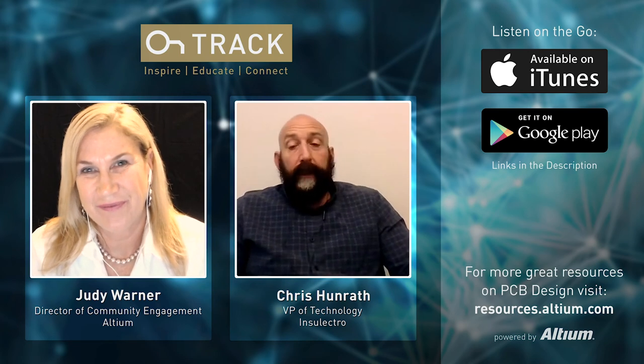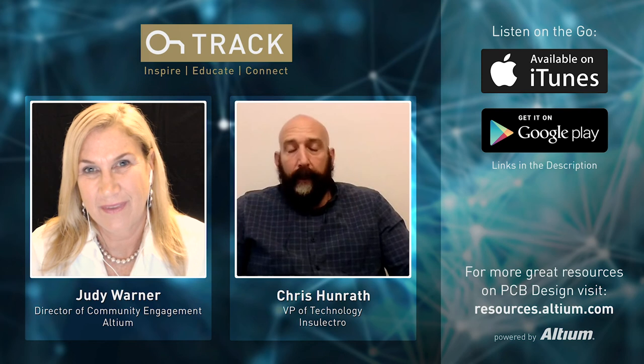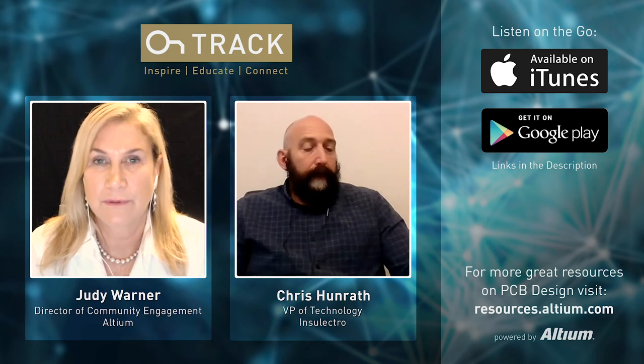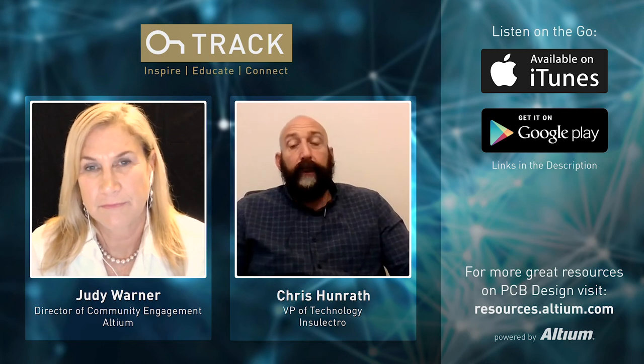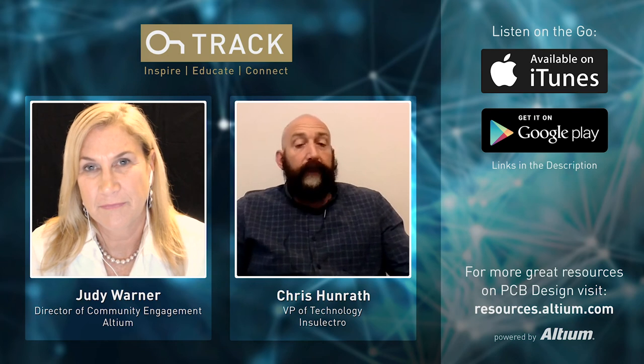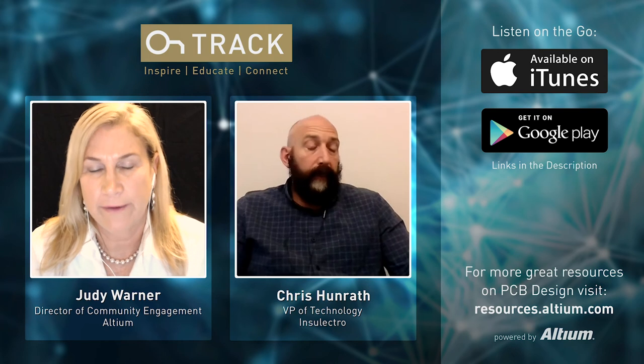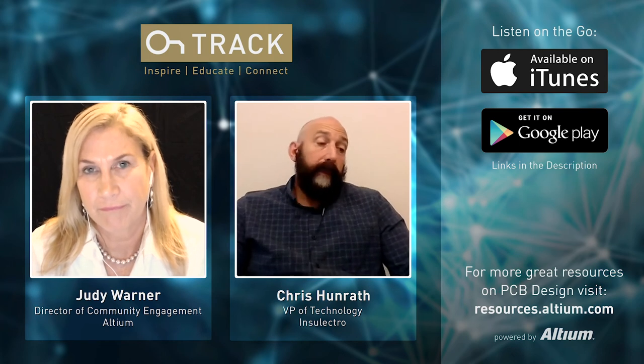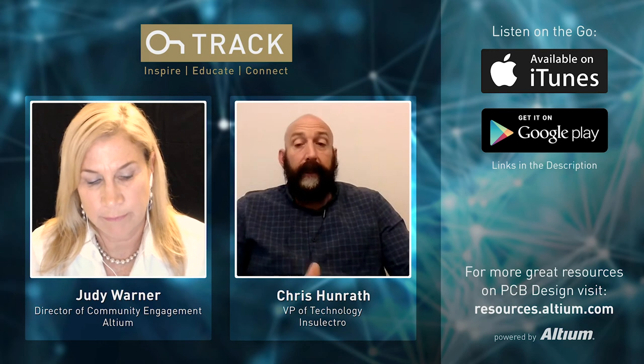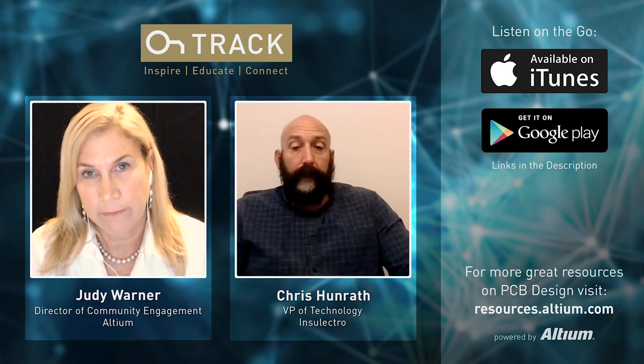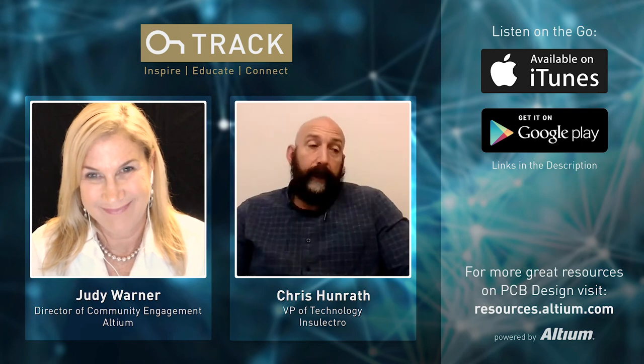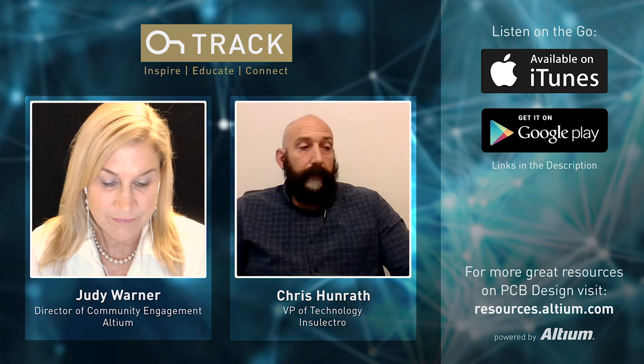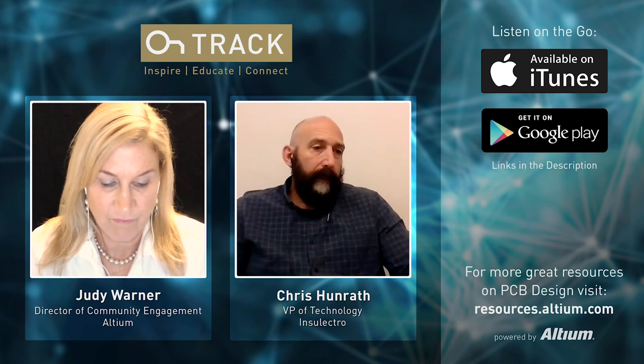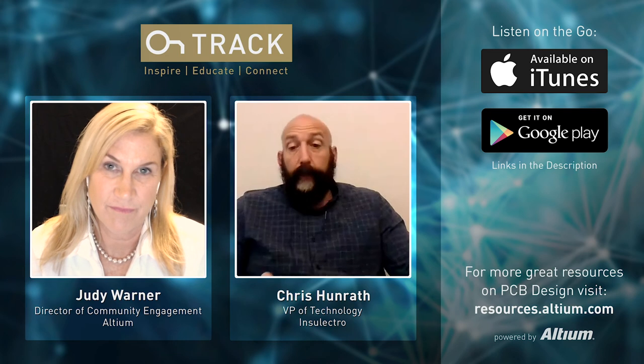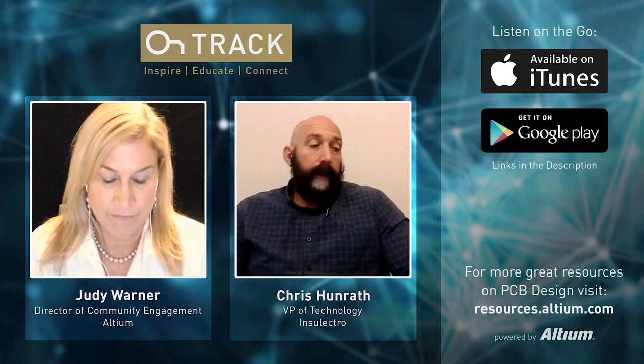But actually, we're seeing a trend. A lot of our customers are buying laminating equipment. And right now, that's a whole other story because lead times are way out on equipment in general. But what we're seeing is people are making sure they have that high temperature capability. And it's not just for something like HT, it's for LCP and FEP as well, fluoropolymer film. They have some good electrical and signal properties, and that's a big deal these days. Performance-wise, they're very good. They're harder to fabricate, but they do have some good properties. Even, as we talked about last time, glass reinforced PTFE materials, some of them require high lamination temperatures.